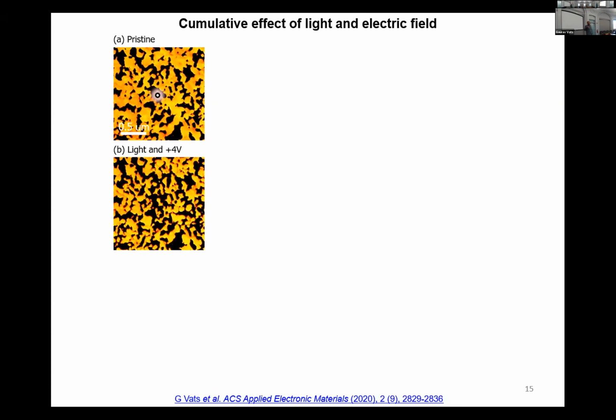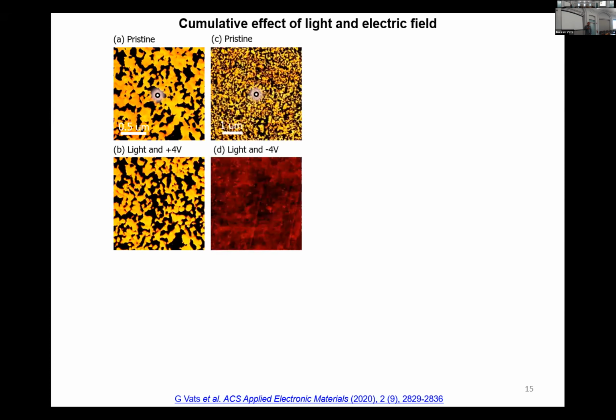Now, let's see what happens when we use a -4 bias, basically a different direction. So I acquired this image, which is pristine. The scale is bigger in comparison to the first figure. So it is like 4 by 4 micrometers. Again, I placed my tip at the center. I shone light, I applied -4 volts for a few seconds, and I did the measurement again. You can see the domains are completely flipped. So you don't see any yellowish colored domains here. So there is a large area switching within a few seconds.